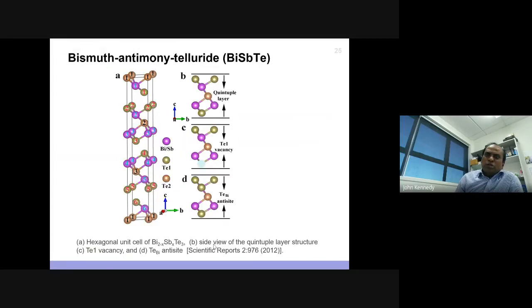And so why bismuth antimony telluride? As I said there, the heat structure and the Peltier cell. The biggest advantage is that it is a narrow band gap semiconductor. If you look at the crystal structure, tellurium is in a vacancy site, and tellurium and bismuth are in antisite locations as well, which tells you that maybe you can manipulate the lattice and antisite locations of these materials and change the crystal geometry. You can create a few more vacancies and see what happens in terms of the conductivity. So we looked at it carefully.